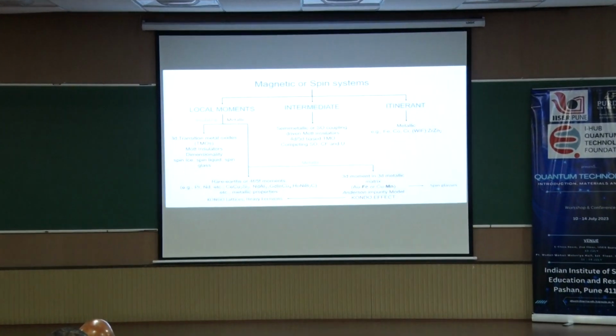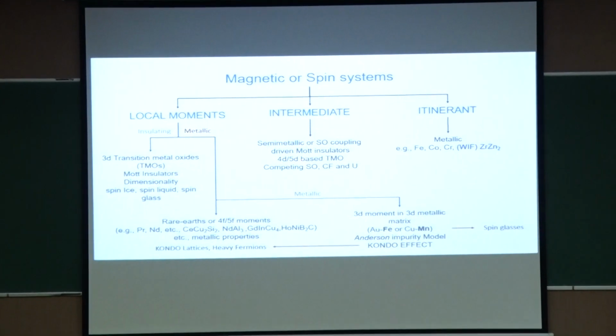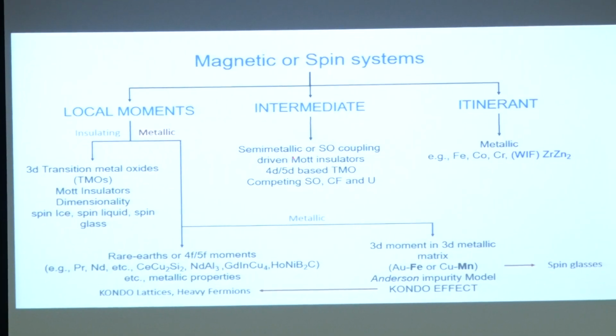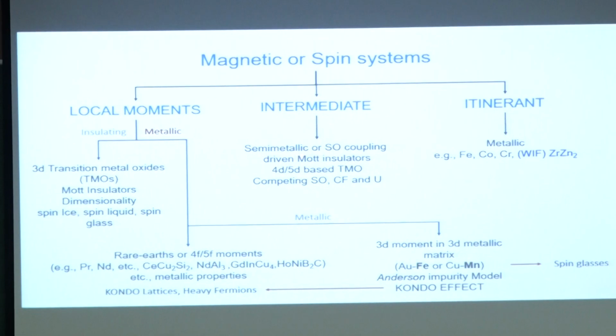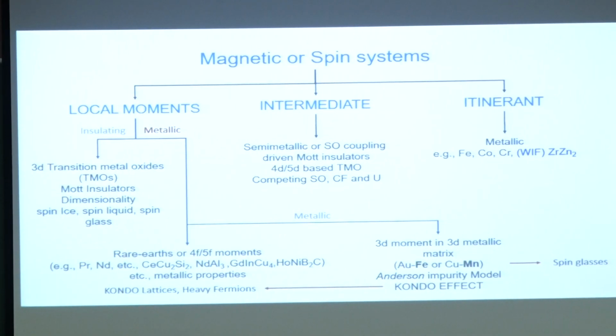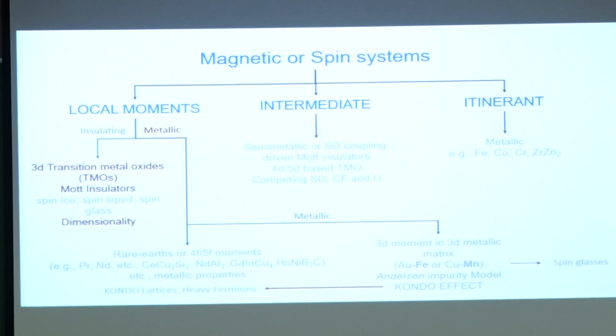And then in between these two, if you look at 4D, 5D transition metal oxides, there you get a situation which is akin to the situation that you come across in 3D transition metal oxides, which is the Mott insulator. But here the Mott insulating ground state is driven by the spin orbit coupling, all right, not the usual on-site Coulomb repulsion. So this was a very broad map of how the magnetic systems can be classified.